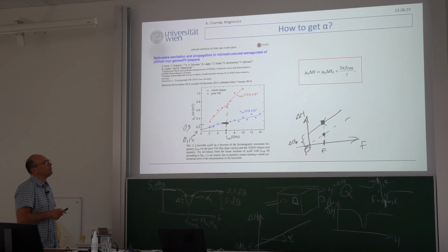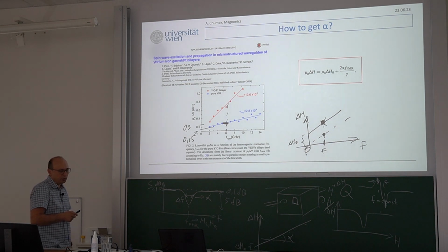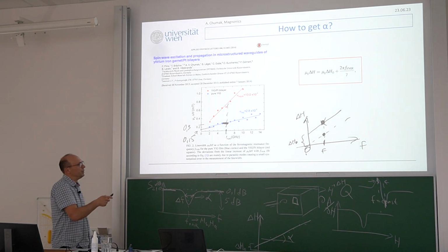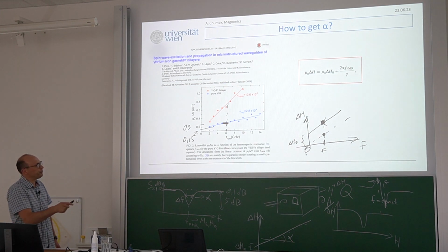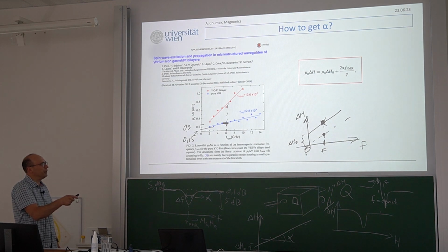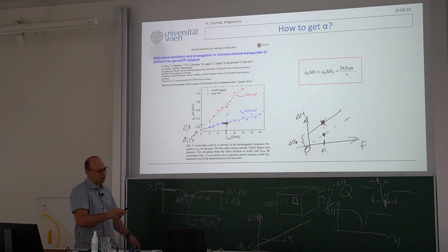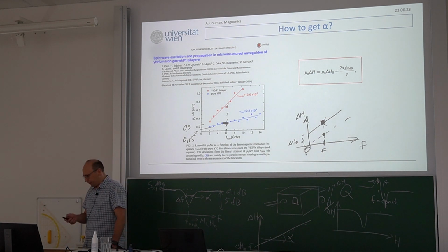But it's known that for thin YIG, after you place platinum, a material with large spin orbit interaction, on top, there will be an increase in damping of around 3-4 times, and that's exactly what you see here with this red curve, that damping is increased, particularly in terms of alpha. Yes, so maybe this would have similar or close delta H0, but alpha is increased, so damping in your sample increases.